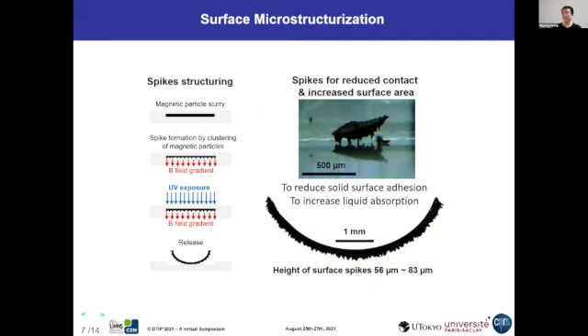In addition to the self-transformabilities, we can also program the surface microstructuring of the soft streamer. We use the same magnetic particle slurry, and in this case, we pull it down with an external magnetic field gradient at the bottom, and the magnetic particles align to form tiny microspikes, with a height between 56 and 83 micrometers. This helps us reduce solid surface adhesion by reducing the surface contact area, and it also contributes to increasing liquid absorption by increasing the surface to volume ratio.